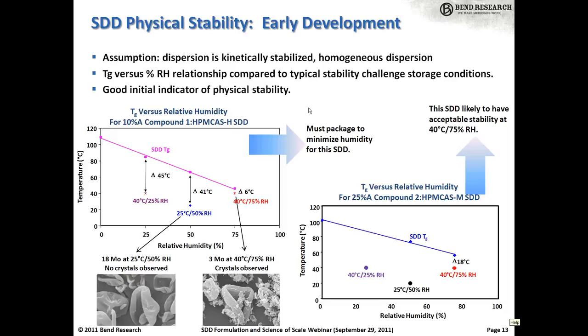This slide describes the use of a rule of thumb approach in early formulation selection. There are two ways you can have a physically stable dispersion. One is if you're lucky enough to have a thermodynamically miscible system where the drug and polymer are in a thermodynamic solid solution at the selected ratio. That's most often not the case, so we go on the assumption that it is not true, and the dispersion is kinetically stabilized. The mechanism for kinetic stability is that when it's stored well below the glass transition temperature, the mobility in the dispersion is low enough that you simply don't observe phase separation and nucleation of crystals at any relevant time scale.